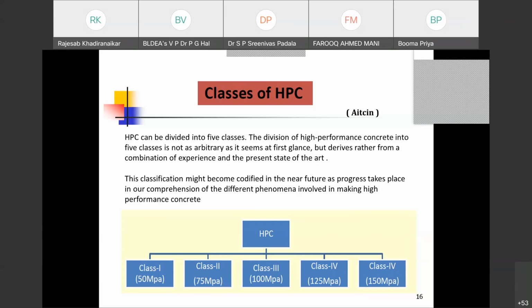So HPC class 1 is up to 50 MPa, class 2 is 50 to 75 MPa, class 3 is 100 MPa, class 4 is 125 MPa, and class 5 is 150 MPa. Of course, some people have produced in laboratory conditions more than 150 MPa also. But in our case, in our laboratory, we have produced up to 120 MPa. Worked on mechanical properties, 2 PhD theses we have produced up to 120 MPa.